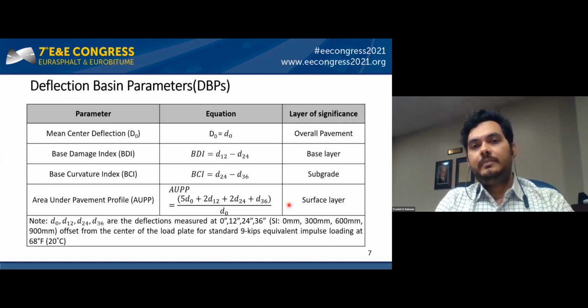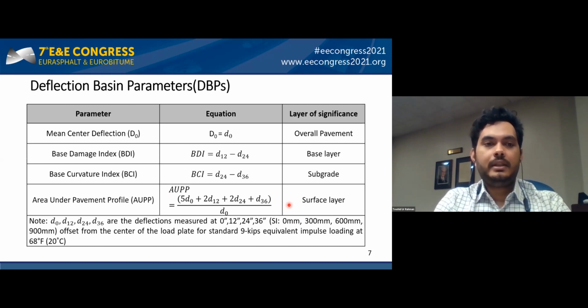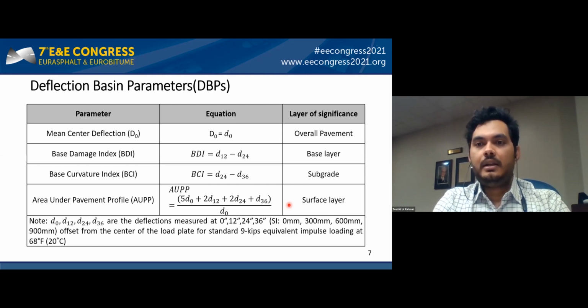The deflection basin parameters that we analyze are: the mean center deflection D0, which represents the overall pavement structure; the BDI, base damage index, which represents the base layer; the BCI, base curvature index, which represents the subgrade; and the area under pavement profile, AUPP, which represents the surface layer. The D represents the distance from the center of the load plate to the geophone measuring the deflection.